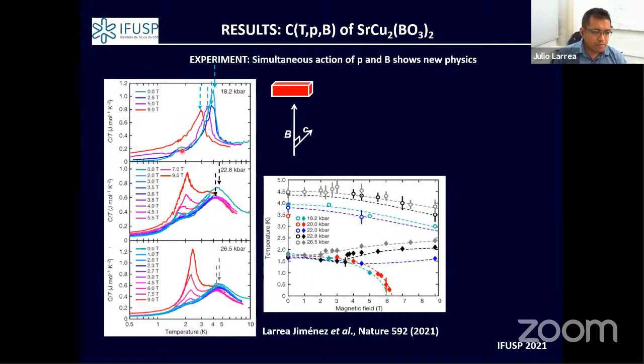And the same also for the other pressures, you can see it decreasing in this way. For the small anomaly, what you observe is a completely strange trend, because for 18.2 kilobar, for instance, this small anomaly with application of magnetic field is decreasing until it is suppressed completely, suppressing almost at 6.5 Tesla.